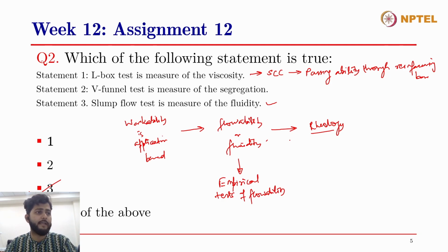but surely it is not the right test to identify segregation in concrete. There are segregation resistance tests, or in the case of bleeding, there is the pressure bleed test, and all those different tests that can be done in order to determine the stability of fresh concrete. But yes, the V funnel test can also be used to get an idea of whether there is segregation in the mix. I know of certain European guidelines or standards on self-compacting concrete mixes where they use the V funnel test. Initially they carry out a V funnel test at T0, and then again they fill the V funnel and let the concrete settle in it for 5 minutes, and then do the V funnel test again. If within the 5 minutes the V funnel times vary greatly, then this could be a sign of segregation. But there is no direct relation of segregation with the V funnel test.